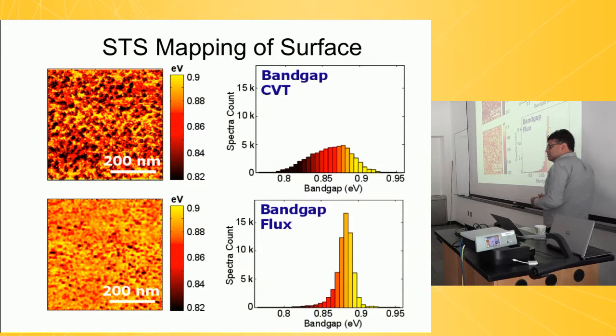We chose 500 nanometers because that's a typical diffraction-limited optical spot. So if you have an optical spot at your best resolution, you're averaging over this area of the sample. And this is what, locally, the gap of the material looks like. It varies from about, in this case, 820 millivolts to about 900 millivolts. This is for one of our crystals that's not the best, the vapor transport grown crystal. This is on the flux crystal.